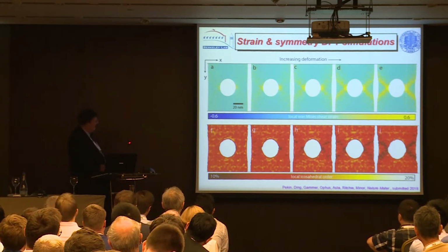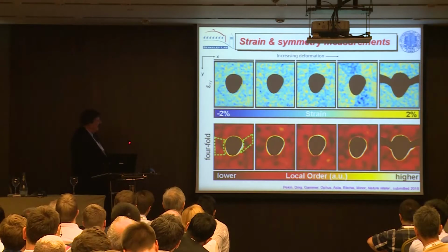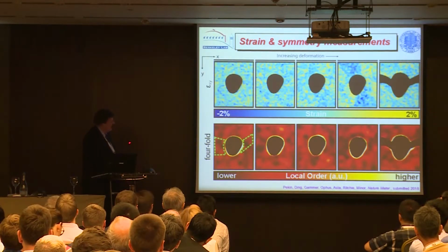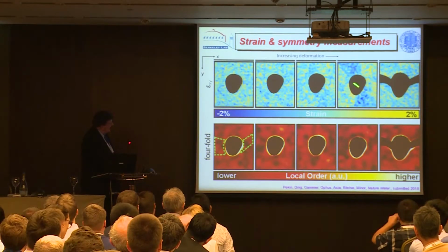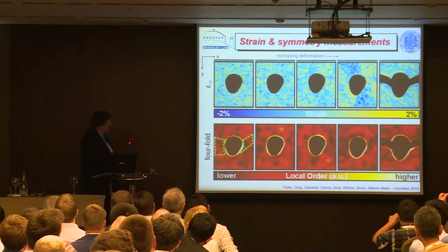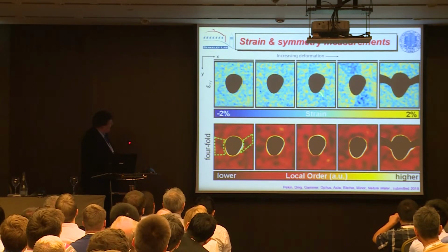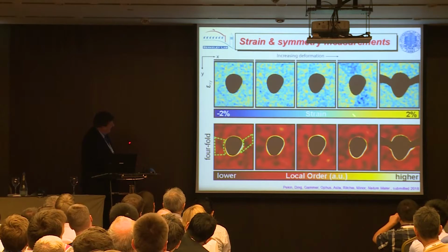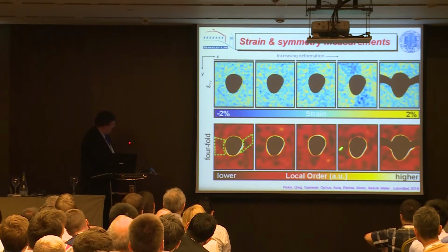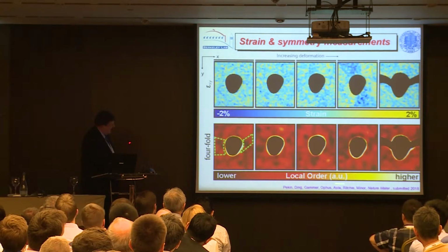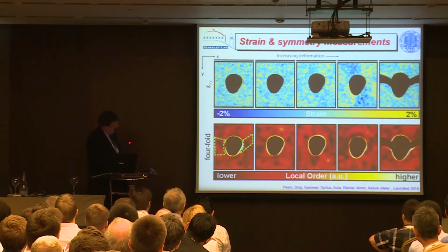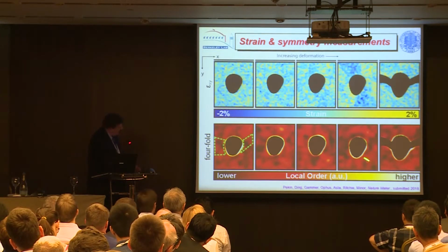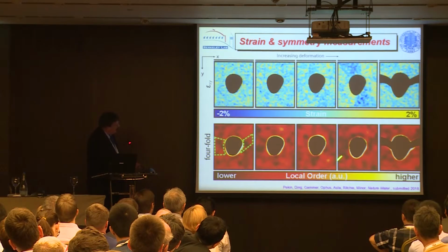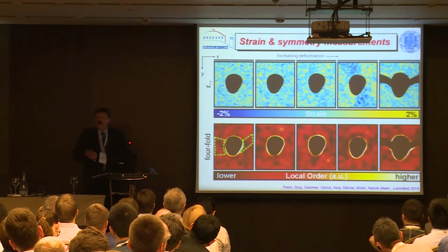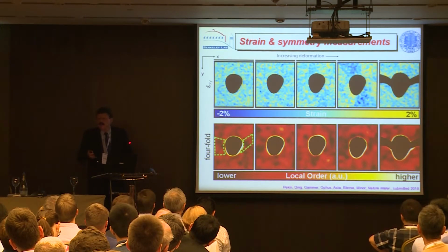So that's what the DFT shows us. And these are our images. This is the first one we've taken. You can see again, not all are very clear, but this is indicating the regions of the shear strain here, these yellow regions here, and this is looking at the fourfold symmetry, the local order, and you can see, we can start to see regions in the same location where we're getting a reduction in the local symmetry.